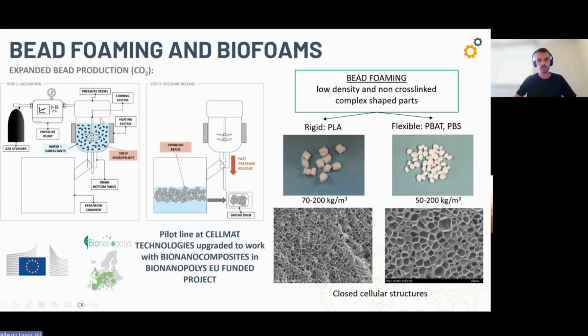This is the foaming pilot line. The bead foaming equipment we have has been upgraded in a previous European funded project by the Bionanopolys. So this equipment is upgraded to work with several biopolymers and even nano-based composites. So this is the target in this project, to work with bio-based nanocomposites. And we have been able to produce foams by bead foaming using different biopolymers and with different cellular structures and cell sizes. Here you see some examples: rigid PLA with closed cellular structure within this density range, and flexible foams with closed cellular structures within this density range.